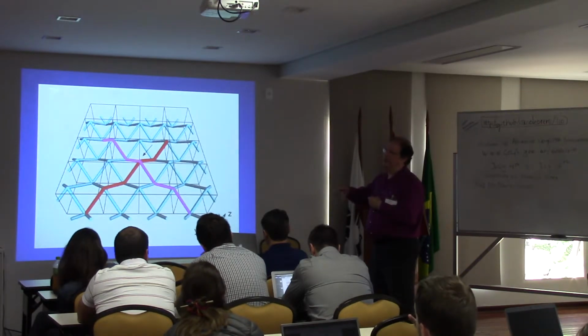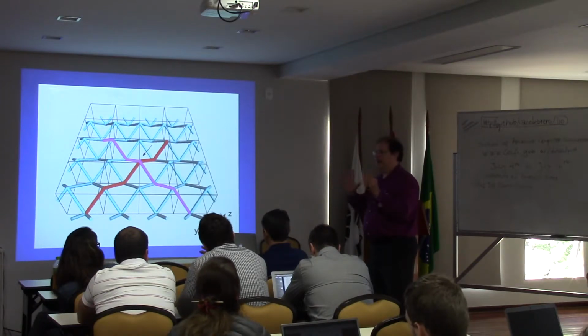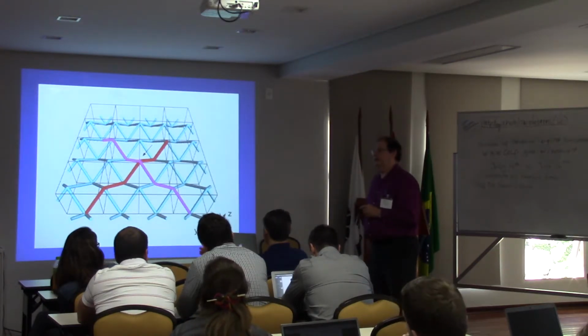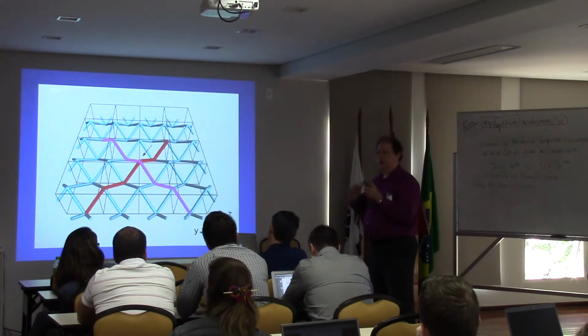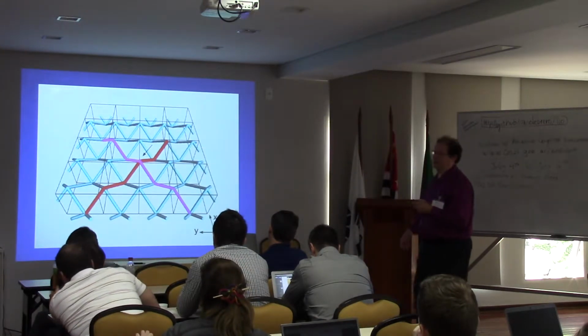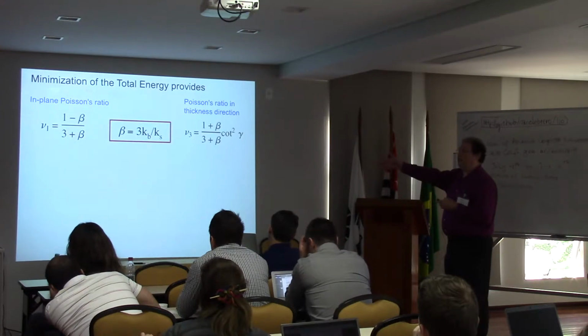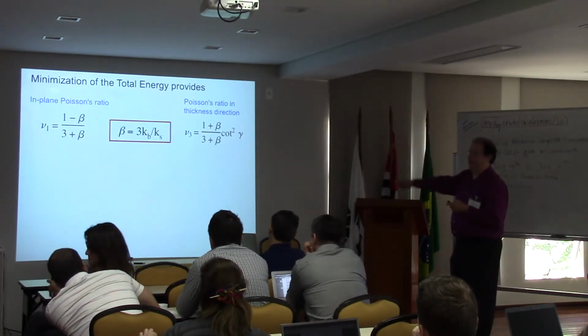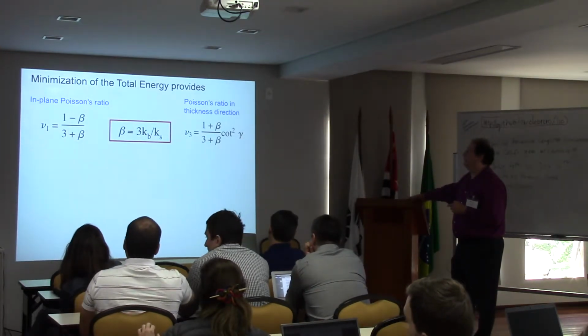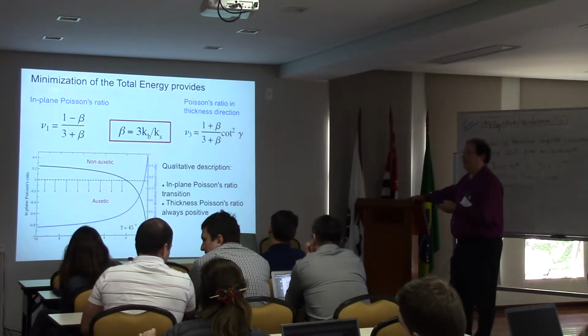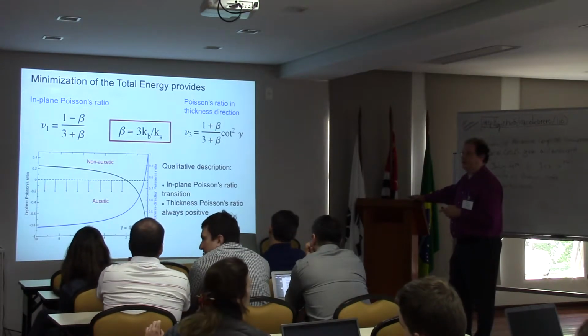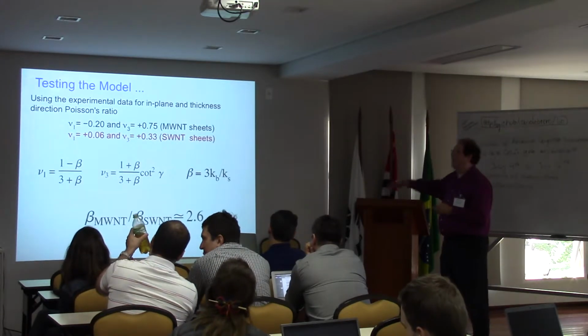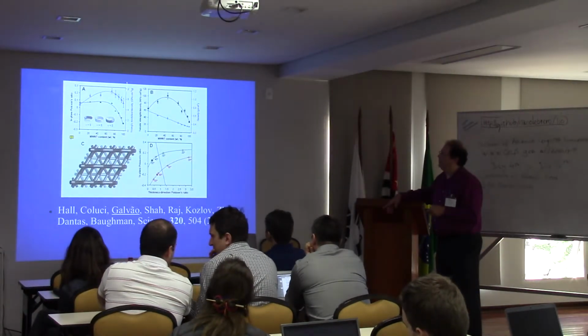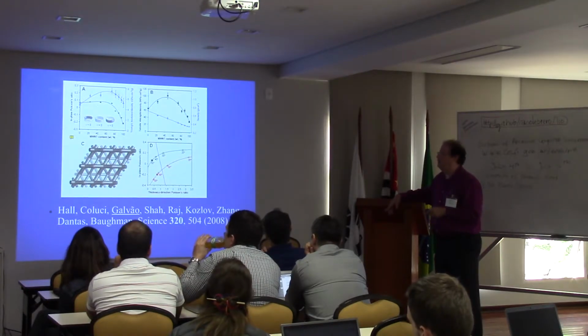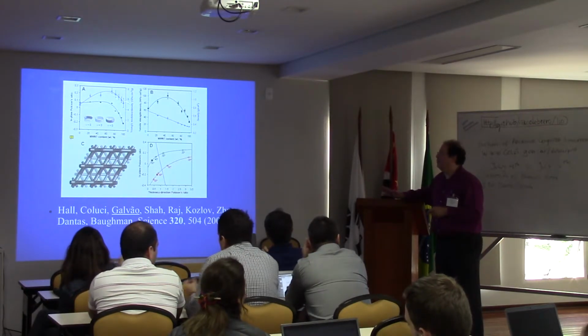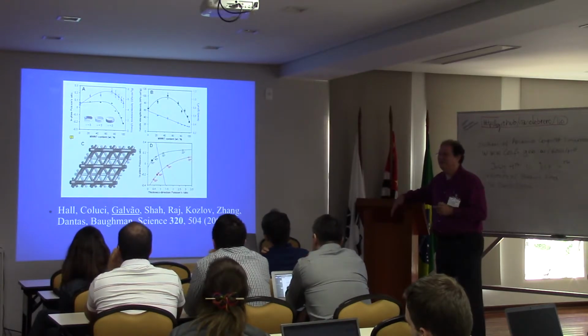So we play with it, and it's a trial and error approach, guided more or less by the data we know for the carbon nanotube; we know more or less the range that a carbon nanotube should exhibit. Then you use analytical mechanics to derive the expressions for the in-plane and out-of-plane, and see if they reproduce the transition, and most important, if you get numbers that fit the experimental data. This is the error bar. It's amazing that if you consider the error bar, it's almost perfect.